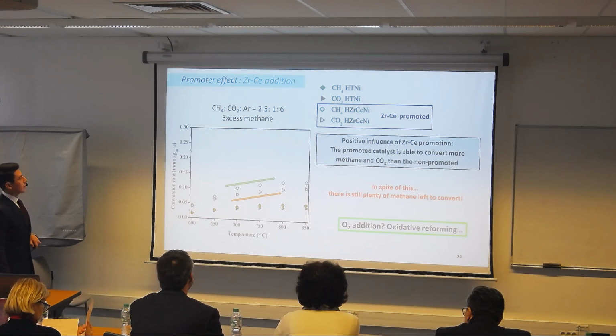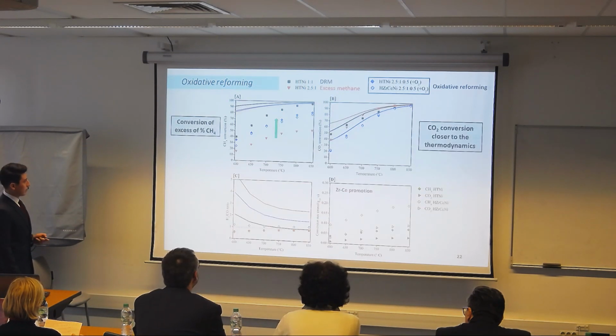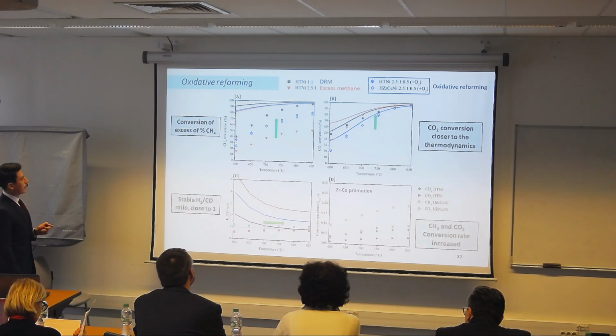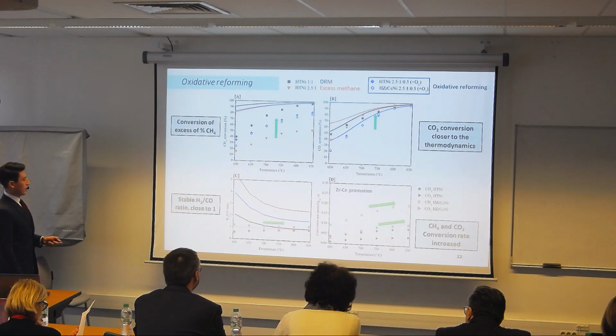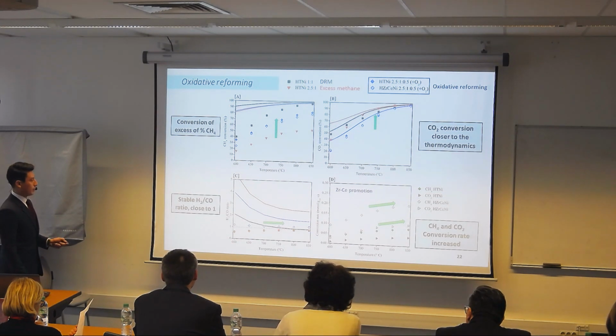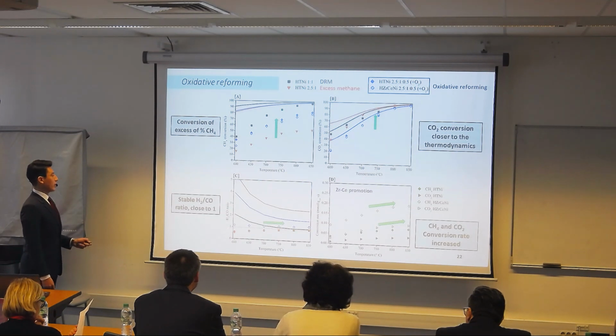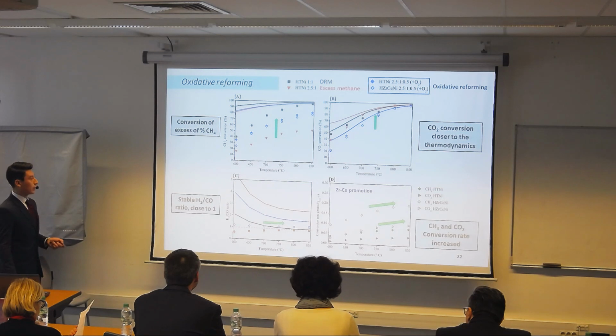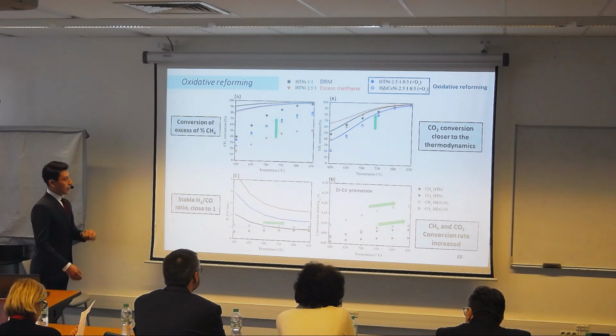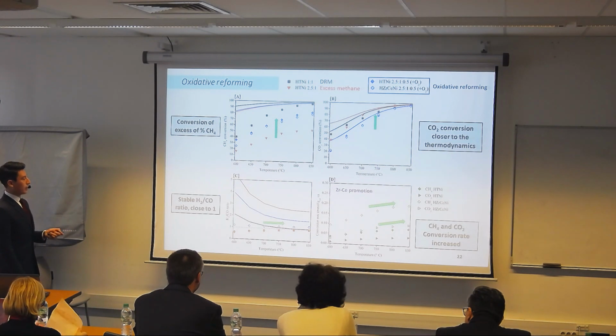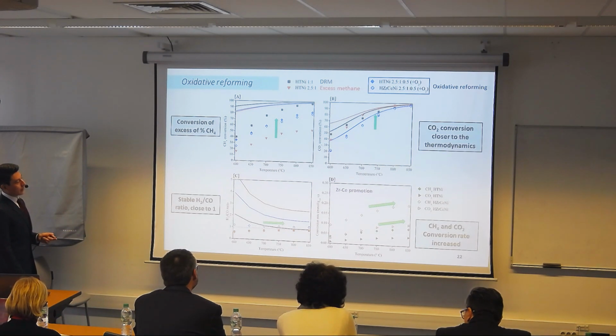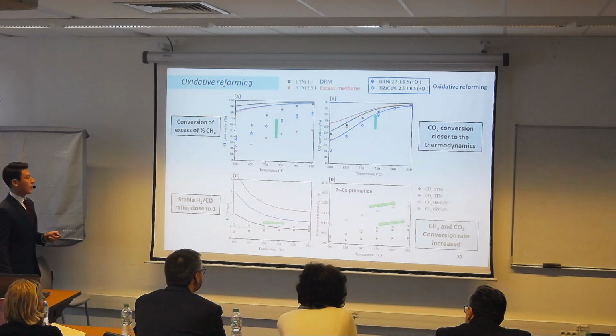So now we are going to introduce oxygen in order to see what is happening in the oxidative reforming. We can see now that the excess of methane is getting converted in the samples. Also the CO2 is getting closer to the thermodynamic value, and the syngas ratio, one of the main objectives for this reforming, is getting over the unit. So this is a very good result. Talking about the conversion rate, we also have an increase of the conversion when we add the promoter